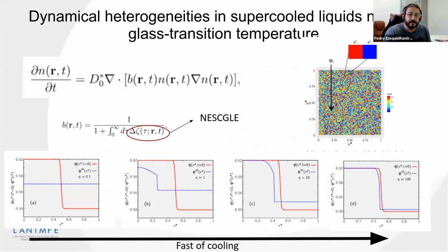Regarding the dynamic heterogeneity problem, we will start from a linearized version of the diffusion equation, for which the time-dependent mobility is included explicitly. As you remember, we are able to calculate this time-dependent mobility from the NESCGLE theory. Then we consider a system which is divided in many small cells, each one with a local time-dependent density. So we focus on two adjacent cells and how a prepared fluctuation, I mean an initial condition with different density at each cell, relaxes to the final state after a cooling process.